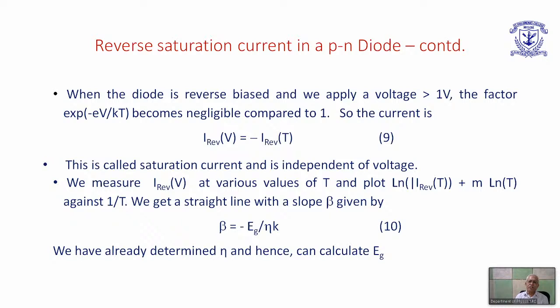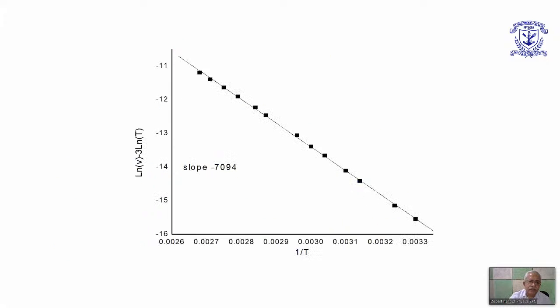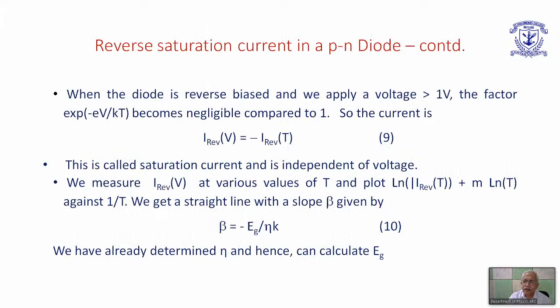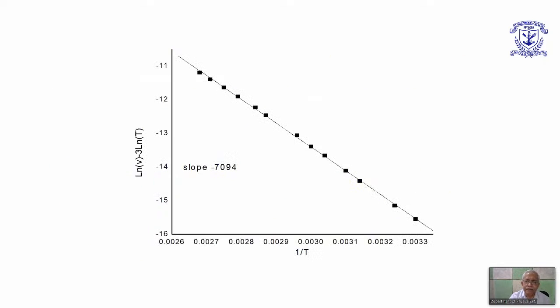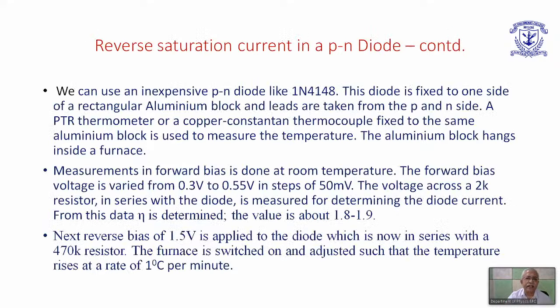Since from the first experiment we have determined eta, and k is Boltzmann's constant, beta is the slope of the new graph that we have generated. Therefore, Eg can be evaluated. So here is a graph of log I reverse plus m log T versus 1 by T, and it's a straight line. We see that the slope is something like minus 7,000, and one can determine the band gap.